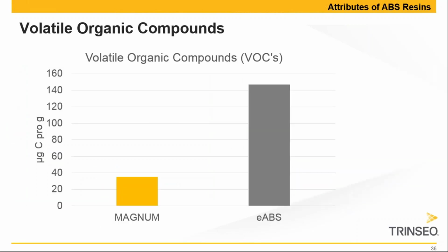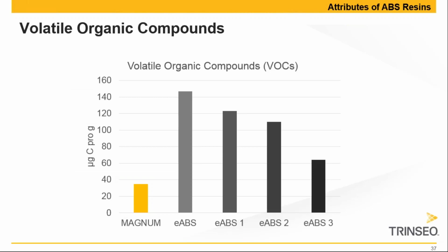We move to the next ABS attribute, which is volatile organic compounds, or VOCs. We have expressed them here as microgram carbon per gram of polymer, and we see about a factor 4 more VOCs in the high impact emulsion ABS from Asia Pacific versus Magnum 3904. If we compare the same experiment to a series of other emulsion ABSs, the message is fairly similar. Also, other emulsion ABSs from the Asia Pacific region have significantly more VOCs than Magnum, almost a factor 2 to 4 higher.